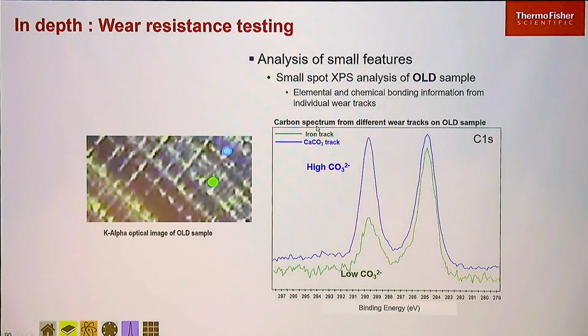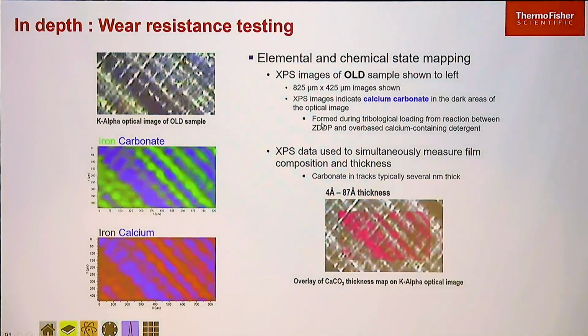So is this true across the sample? Well, we can start to investigate different areas. We can look on the tops of tracks and in the tracks and see variation again. Even on the good sample, the amount of carbonate in a track or outside a track is different. Then by mapping it, we can look at the distribution across it. So again, on the old sample we can see the variation in the iron signal and the carbonate, and the iron versus the calcium. We can see the calcium and the carbonate signals overlap. So that's giving us a good idea it's probably calcium carbonate that is there.